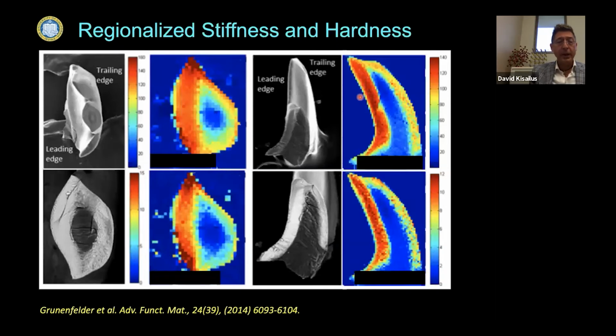And we've done some nanoindentation on these teeth, both on these transverse and longitudinal sections, and you can actually see that the stiffness is on the order of about 140 gigapascals. Hardness is around 13 gigapascals, 12 to 13 gigapascal hardness. So incredibly hard. In fact, it's the hardest and stiffest biological mineral known.